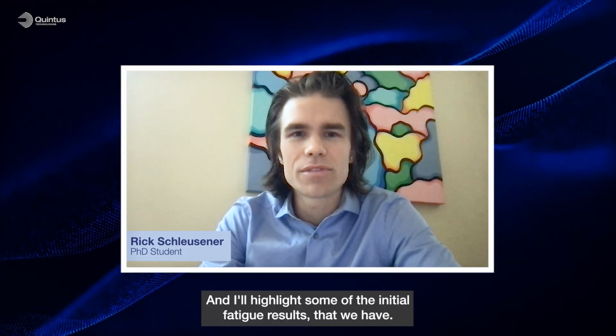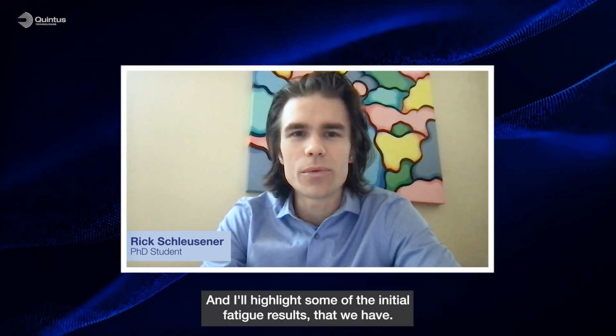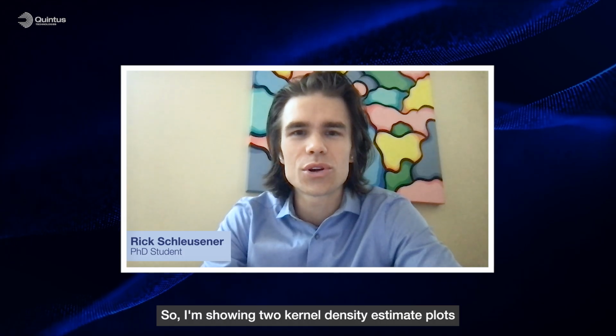And I'll highlight some of the initial fatigue results that we have. So I'm showing 2 kernel density estimate plots, essentially histograms showing the distribution in cycles to failure for our stress relief metal versus our HIP metal. And we've also separated the data based on specimen orientation, both vertical and horizontally oriented metal.